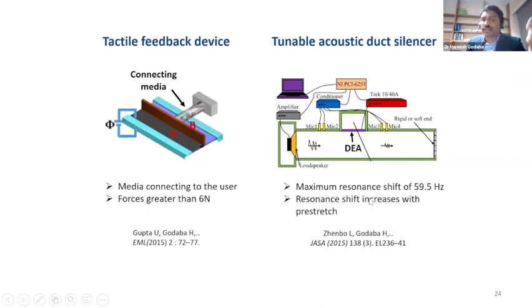So what we can do is we can have a duct silencer whose resonant frequency for attenuation can be changed by controlling the voltage input to this dielectric elastomer actuator. And we also found some dependence of this resonance shift on the initial pre-stretch of the membrane.